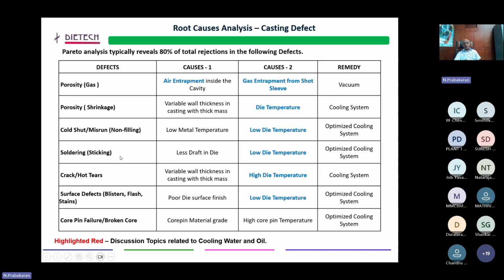Solder will be a common phenomenon, once again related to low die temperature. Surface defects are also related to low die temperature. Core pin failure is also due to high core pin temperature. So we can see all are thermally oriented problems. If we could tackle these temperature oriented problems, we will reduce the rejections in line. Probably I have also given some systems; for gas porosity, I have given a vacuum.